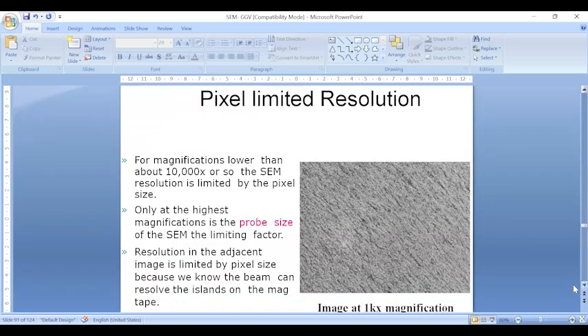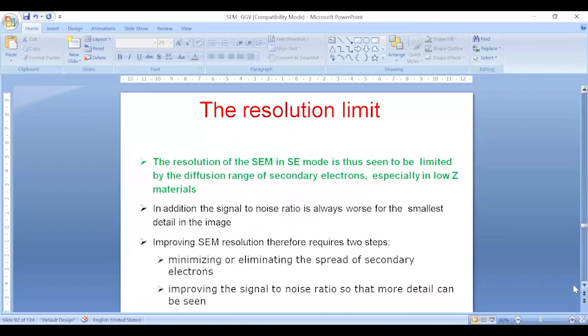So the pixel limitation is behind the resolution, and how much your system can resolve. Generally SEM is 100x to 1000x, but in the TEM more than 1 lakh x can be resolved, so we can get the image at the angstrom level, the atomic scale, in a TEM, but in the SEM only the nano region. And as I told you, there are two types of detector: the backscatter detector, also called a solid state detector, and the secondary electron detector.